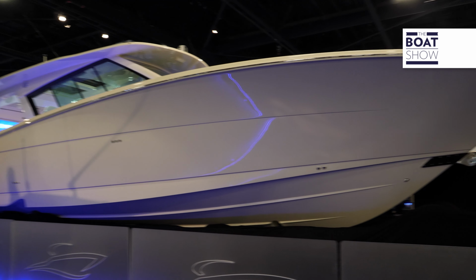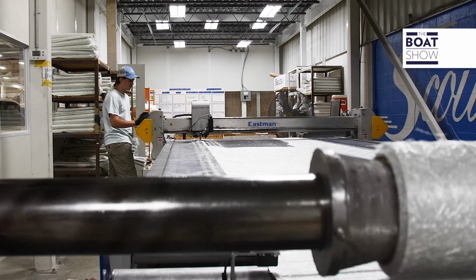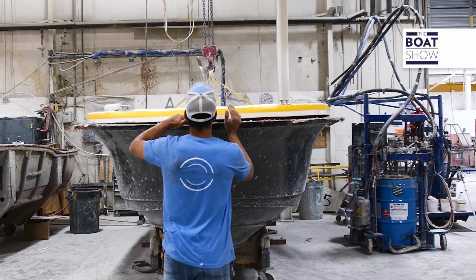Yeah. So, to your point, the style is the most important thing to the consumer, to be able to identify that boat, and our off-white, kind of pearl color helps do it. The lines, the Carolina flare, the broken shear line, and then we built them second to none, really. I hate to sound conceited. I'm not the owner of the company, so I guess I can say it, but we're 100% hand laid all the way down to the smallest part of the smallest boat that we build. And then once you get up to our S-Class series, we're epoxy infused. We actually bake those hulls in the mold at around 145 degrees for 8 hours.